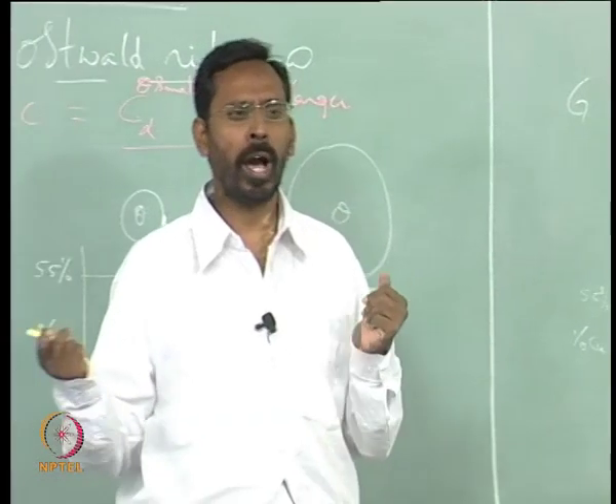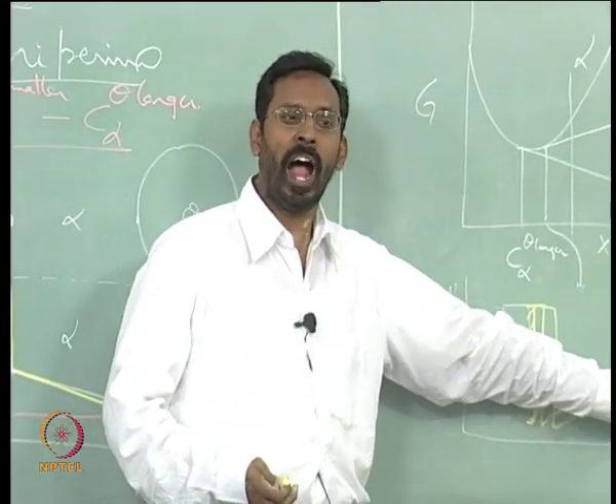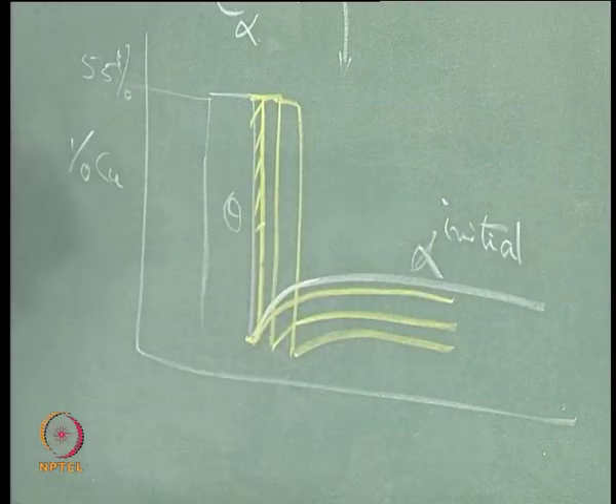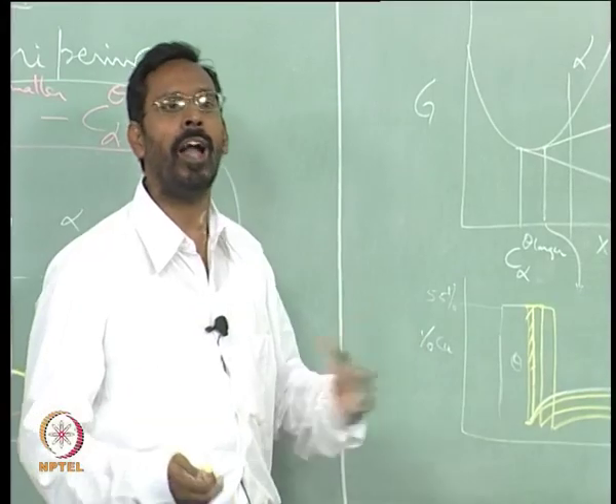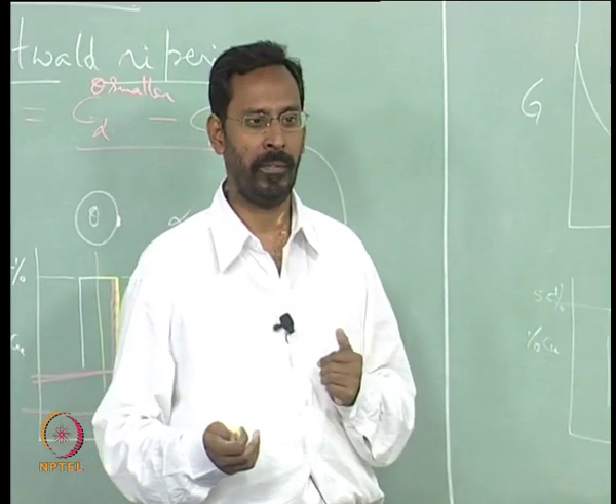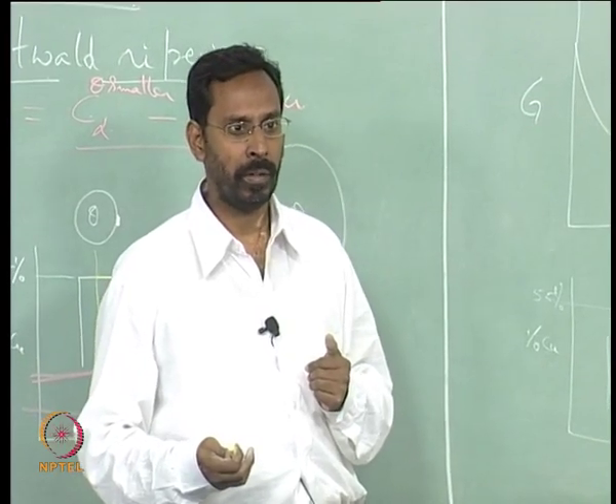And where do these copper atoms come from? They cannot come from thin air, they have to come from the alpha only. And as the alpha supplies more and more copper atoms to theta, alpha gets depleted in copper. How can it cause further nucleation when it starts growing?